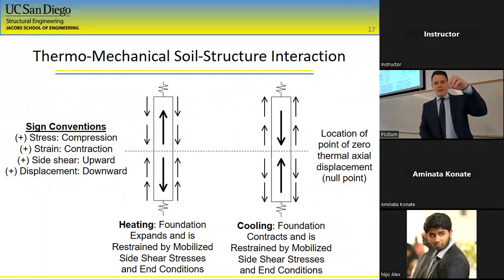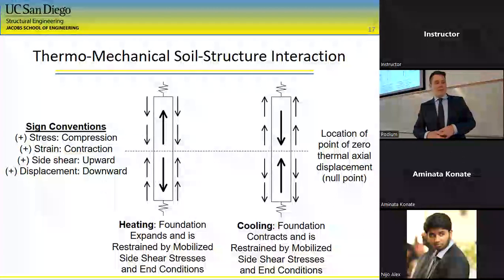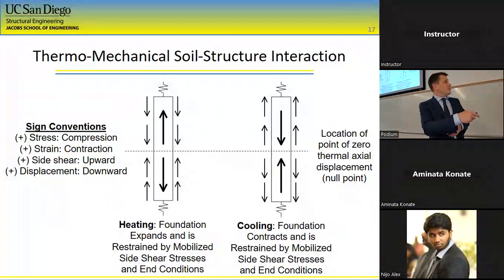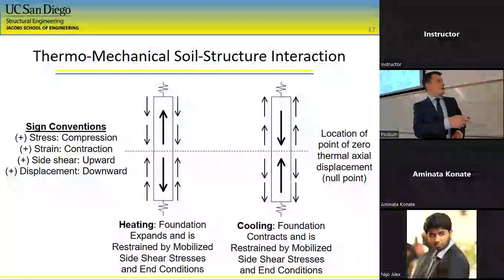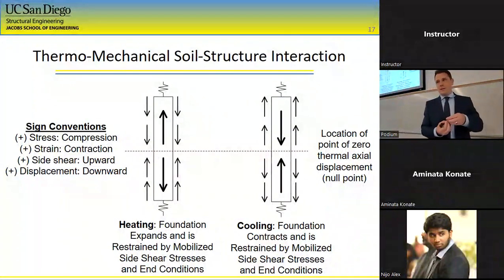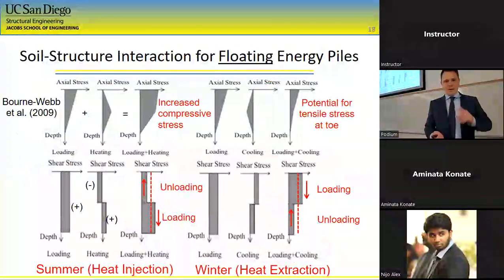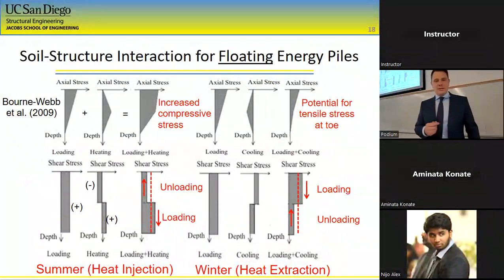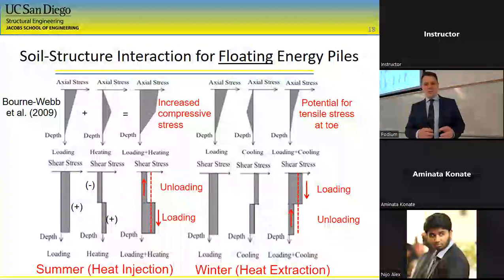So the pile is expanding about its null point. It's not necessarily about its center. And you're having restraint due to the building above, the toe at the base, and then side shear on the bottoms. And then when you're cooling it, it's contracting. And depending on the restraint provided, you could potentially have tensile forces being induced in your pile. But it's important to note that these stresses are going to be superimposed onto those due to mechanical loading.